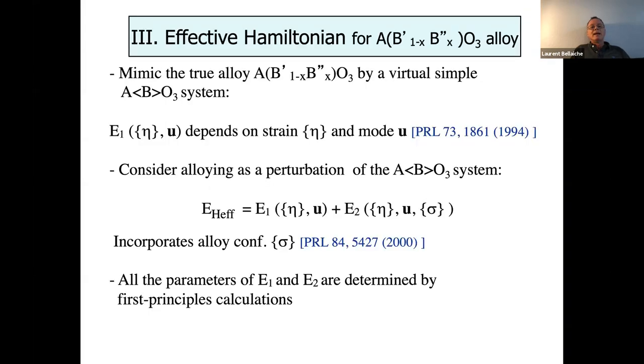So you have some kind of needle-like correlations along a specific direction, and this is indicated in the paper on the bottom left. And now, this is in fact the first time I looked at effective Hamiltonians, when I was a postdoc with David Vanderbilt. And what we did is to develop an effective Hamiltonian for solid solutions. So how did we do it? We did it in two steps. We say, okay, there are B prime and B double prime ions, let's say titanium and zirconium in PZT. We are going to replace this titanium and zirconium by a virtual simple system. So we are going to generate something that does not exist, an average B, for which the potential is some kind of compositional average between B prime and B double prime. If you have a simple system, you can use the effective Hamiltonian energy provided before for a simple system. And this is what we did.